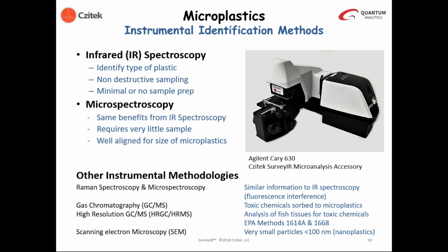There are other instrumental technologies, of course, which are required to fully analyze microplastics and characterize the microplastic problem. Raman spectroscopy provides similar information to infrared spectroscopy. Because of the wavelengths of light employed, Raman spectroscopy can analyze samples that are smaller. However, one has to deal with the fluorescence interference, and in particular, microplastic samples are coming from the environment, and they can be in a complex matrix. So fluorescence due to contamination, other contamination at very low levels, can render Raman analysis a non-starter in some cases.